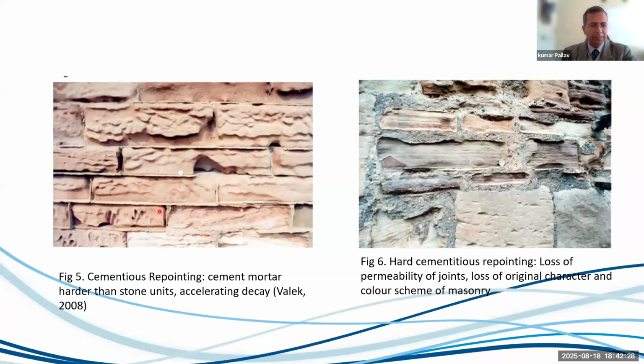So if you see in this cementitious repointing, the cement mortar comes out of it, right? If you see, and then slowly it deteriorates. So your cement mortar is harder. Like if you see, it has started deteriorating the older material, like the brick. If you make a mortar which is harder than that and treat them with it, definitely it will deteriorate that material. Similarly, if you use a hard cementitious material, loss of permeability of the joint will occur, and the original character and color scheme of the masonry will change.